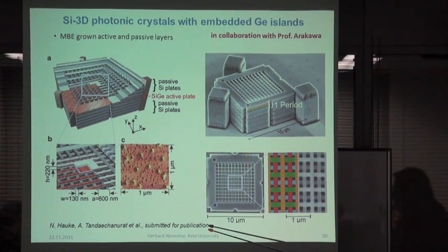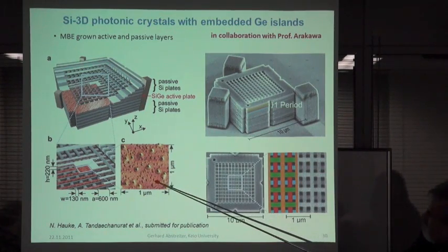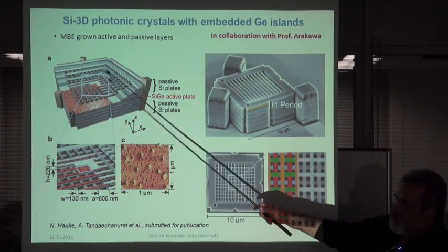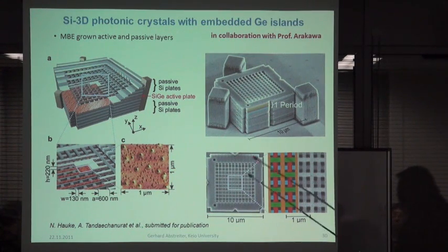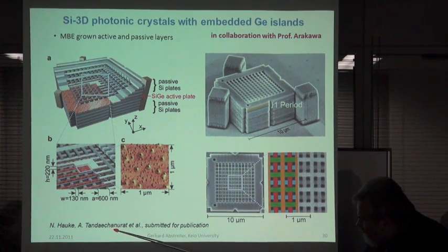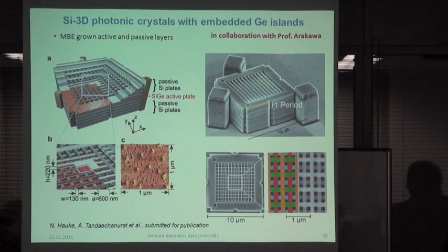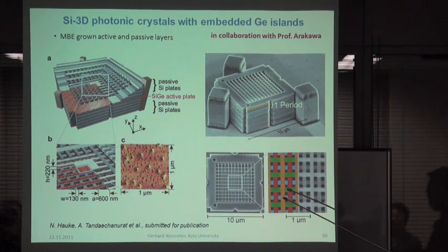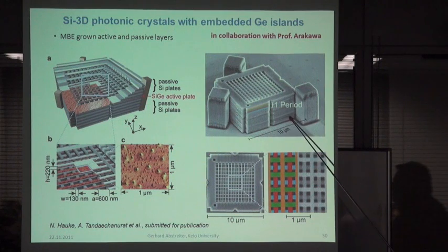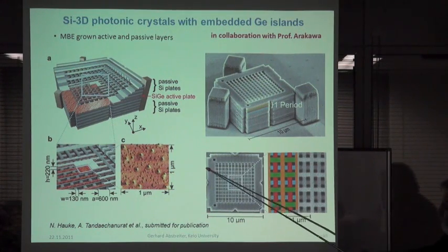And together with a group of Arakawa, we started using the same germanium islands now and embedding them in three-dimensional photonic crystals. And this is a very interesting technique, which I think only Tandaechanurat can really do, in a special SEM electron microscope. So what we did, we prepared in Munich all these platelets. All is MBE grown, so passive layers and the active layers. And we did electron beam lithography. We have exactly the same e-beam writing system as in Arakawa's lab. And we just used the parameters they used. And then he came with a lot of these platelets.